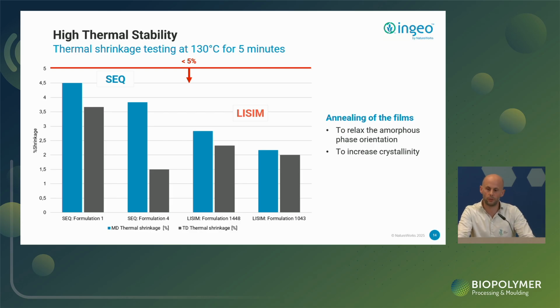after the extrusion process, we have achieved heat shrinkage at 130 degrees C for 5 minutes, which is well below 5%. And that has been really a great achievement if you consider PLA as a not heat-resistant material, due to the annealing process and also this strain-induced crystallization that you can generate in the process. We have really generated a film that is very heat stable.